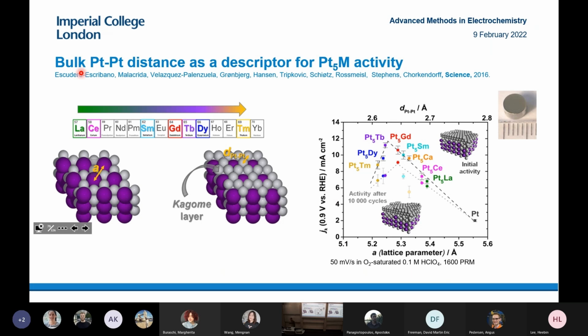We measured a lot of different polycrystalline platinum alloys. And what we found is, as we're going through these different alloys, from smaller and smaller lattice parameters, meaning smaller and smaller platinum-platinum distance, we see improvements in activity, and it peaks around platinum terbium. So this looks like a volcano.